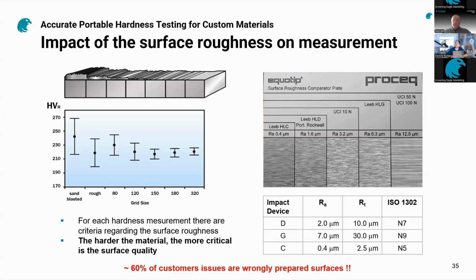Titanium is probably one of the most challenging materials to work with, because of the piling-up and sinking-in effects at the same time. But nevertheless, good statistics would be necessary. I can just repeat what you just said. Nothing to add, Tom.